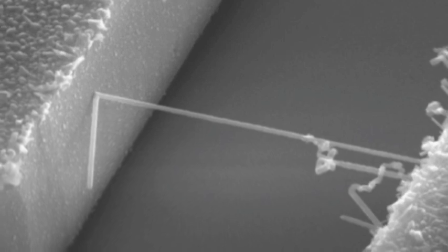We use the fact that nanowires don't mind growing on any kind of substrate. So nanowire of material A will not have any problem growing on material B, although they have a big mismatch in terms of their crystal characteristics.